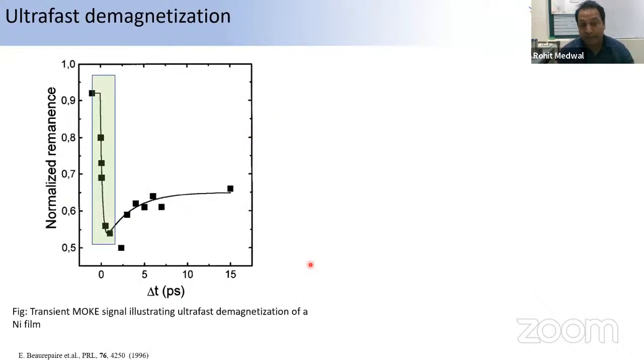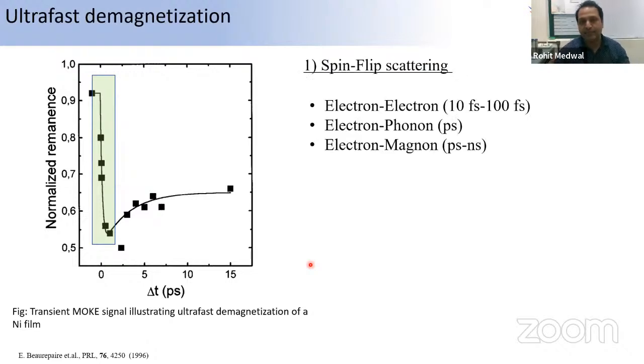People are trying to explain this by several means. They were saying that this is because of electron scattering when you shine a light on the ferromagnetic materials. They were also talking about electron-phonon scattering and electron-magnon scattering. But one should not forget the time scales of these scattering events. They are different. Electron scattering at the ultrafast time scales is within less than 100 femtoseconds. Electron-phonon scattering, because your phonon lattice should not be disturbed, generally happens in picoseconds. But magnons are really beyond the picosecond, in the nanosecond time scale.